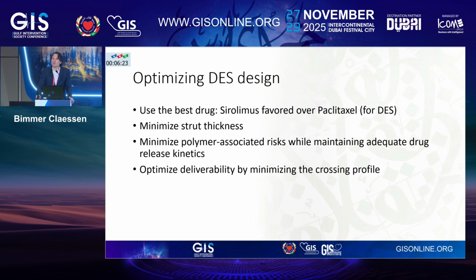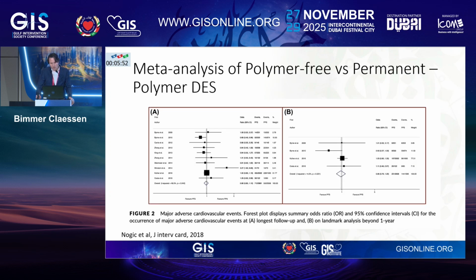So when we think about optimizing drug-eluting stent design, we want to use the best drug. We already know that there's sirolimus, which is favored over paclitaxel. There's no debate over that. We want to minimize the strut thickness. We want to minimize polymer-associated risks while maintaining adequate drug release kinetics, and also optimize deliverability by minimizing the crossing profile. And this is something where the polymer-free drug-eluting stent may perhaps also help, because there's no coating with the polymer. So the stent itself actually becomes a little thinner, crossing profile may be a little lower, and it may be a little more deliverable as a result.